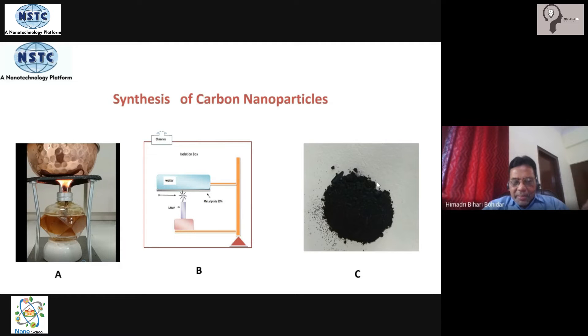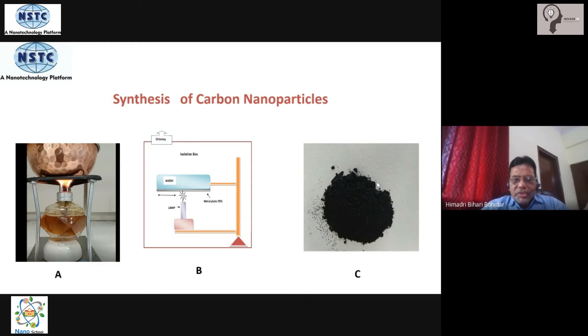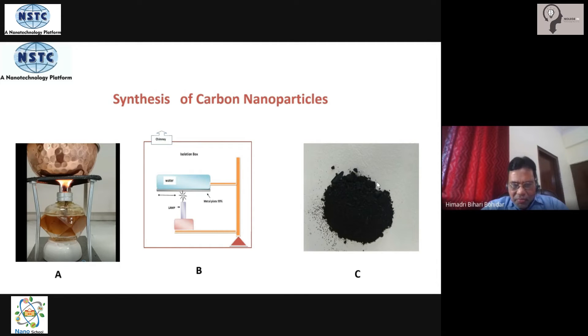The experiment can be done with any metal plate or metal surface. Depending on availability, you can choose gold, silver, brass, nickel, platinum — anything. It will work everywhere, but the morphology and texture of the nano-carbon deposited on the surface changes due to different nucleation and growth processes on different metal surfaces. The plate is continuously cooled so it doesn't get heated up — a container of water is kept there to maintain the temperature.